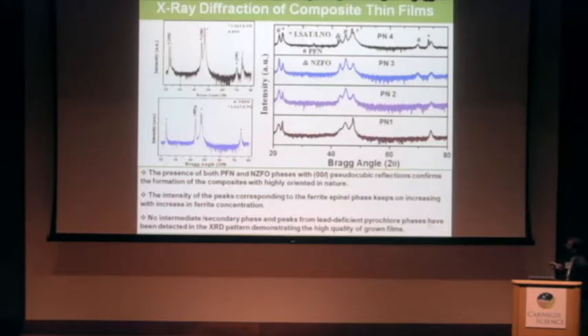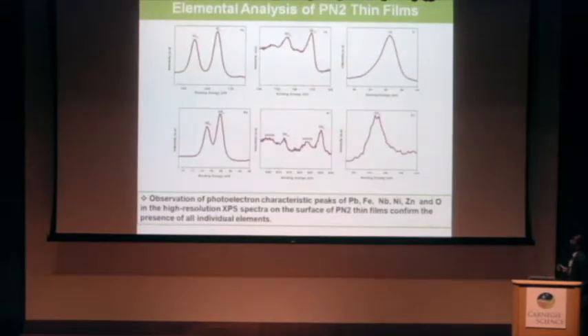With the increase of magnetic content, the intensity of the NZFO peak goes on increasing, and we did not find any intermediate or secondary phases, or peaks from lead-deficient pyrochlore phases. So from the X-ray diffraction, we can tell that the quality of the films is good. In order to confirm whether all elements are present in our thin films, we carried out XPS studies. Here the lead, iron, niobium, oxygen, nickel, and zinc peaks are all present. The observation of all the photoelectron characteristics confirmed the presence of all individual elements. I have presented only this one as representative of all the films.